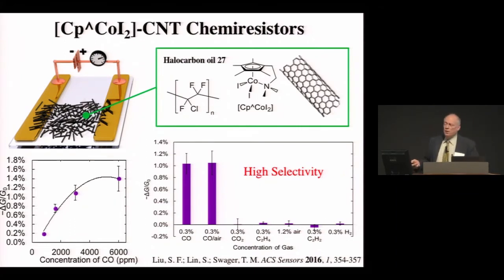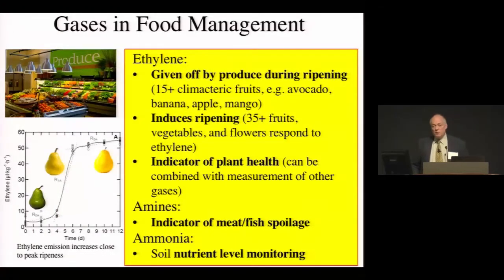I'll come back to that again later, but here's a case where we put this fluorocarbon oil, put this chemical in it, over the top of just some naked nanotubes that we disperse down. And now what you see is we get essentially perfect selectivity for carbon monoxide. And other things that might have kind of similar back bonding characteristics, for the organometallic chemists in the audience, don't seem to really give us any effect. So acetylene and ethylene do not give us a big effect. So that was nice. We had something that had near perfect selectivity for what we wanted by basically looking in the literature at all the kind of wonderful chemistry that's out there that people have designed.